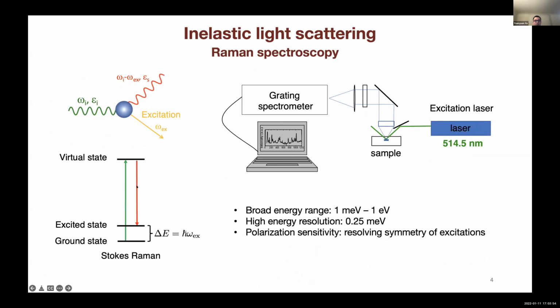The motivation of this work is to study the crystal field excitations of praseodymium 3+ with high resolution spectroscopy. Our experimental technique is Raman scattering of light. Basically, we use Raman scattering to measure the frequency difference between incident light and scattered light. This is a scheme of our macro Raman setup, and it consists of a laser source, optical components, a Cassegrain objective, and a triple monochromator. In our lab, we are able to measure excitations over a wide energy range with very high resolution, and the polarization setup allows us to identify the symmetry of the excitations.